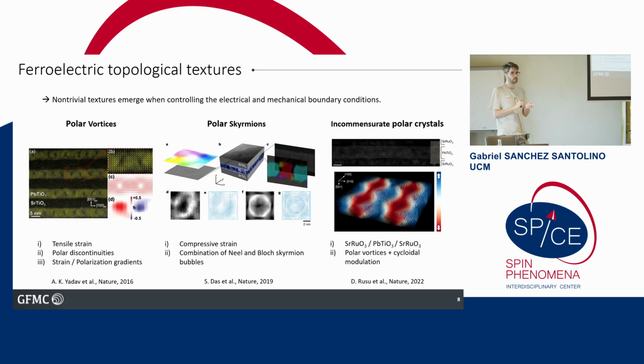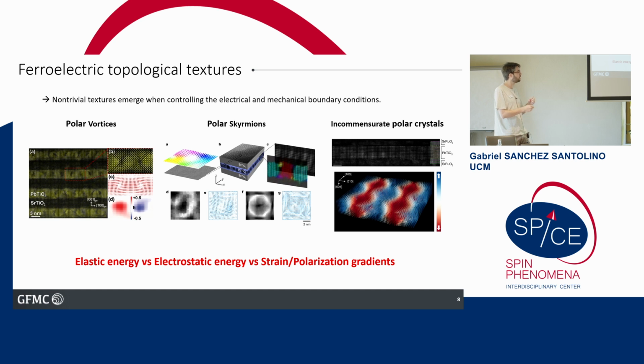There is a different strain, so there are strain gradients that are coupled with the ferroelectric polarization at the interfaces, and you have to carefully choose the mechanical boundary conditions of these little structures to be able to stabilize them. So there is a trade-off between the elastic energy of the strain, the electrostatic energy of the polar discontinuity at the interface, and the strain and the polarization gradients. So if you are lucky, or if you calculate all these parameters, you can stabilize this kind of polar topological structures with the ferroelectric materials.